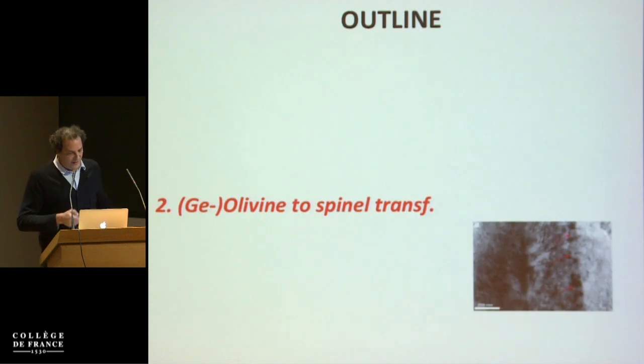So in the second part of the talk, I will come back to some now a bit old results that we've been revisiting, on the transformation of olivine. And we did the experiments, although at the beginning I said that we do everything at the right in situ conditions, we're still not able to do it on the real olivine because the transformation would happen at 14 GPa, and we cannot go to 14 GPa with the acoustics, etc. So we do it on the germanium olivine, which has the transformation at much lower pressure.